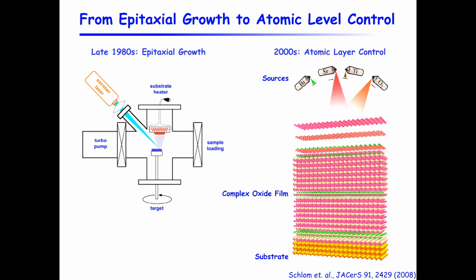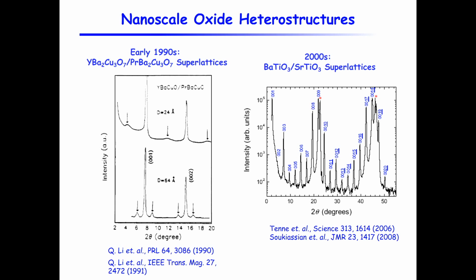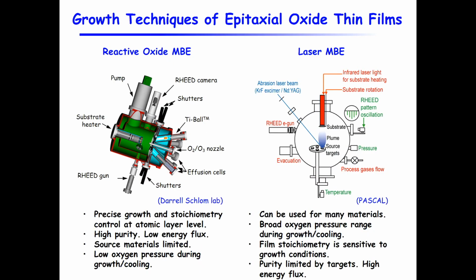Later, in the 2000s, people made progress such that you can make these materials one atomic layer at a time, in particular in oxide MBE, which is allowing people to do a lot of very interesting science. Here I'm showing that in the early 1990s in high-Tc superconductors, the group that I was in at Bellcore and Rutgers was growing YBCO, praseodymium BCO superlattices. At that time, it was very important progress. Then in 10 or 20 years, people could grow these barium titanate, strontium titanate superlattices with all these superlattice peaks, very good crystallinity and stoichiometric control.